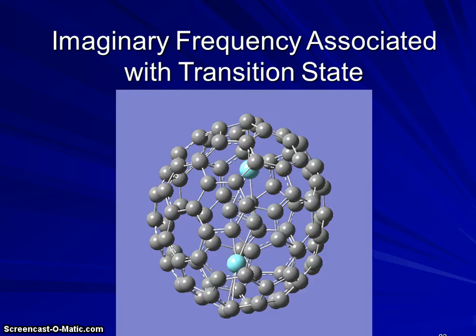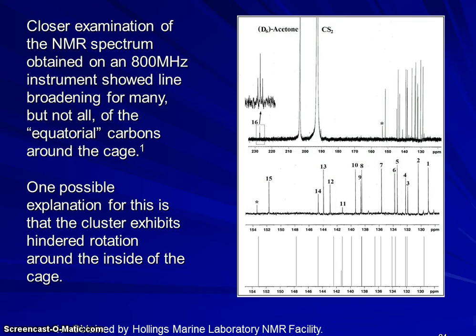So this is exactly what we expected, and so the idea here was that the carbon is vibrating so quickly between those two states because it's such a small energy difference, 3 kcals per mole. It's vibrating so quickly between those two states that the NMR sees the average instead of seeing one state or the other. So we went back to the NMR and ran this on a very high field NMR with lots and lots of scans. Ran for over a month on an 800 megahertz NMR.